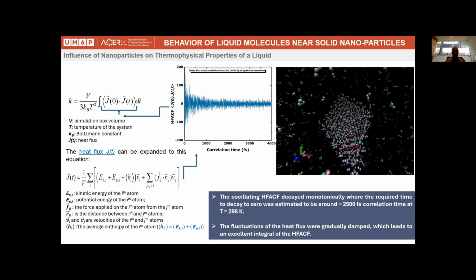So we use molecular dynamics through what we call the Green-Kubo model, which is depicted in this equation. It just shows you here that we can create a system like this with a volume and a number of particles. We study what we call the heat flux, and from the heat flux we can do some integration to get the thermal conductivity in general from this system.